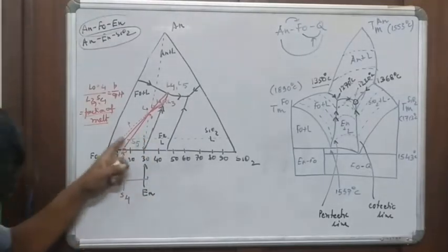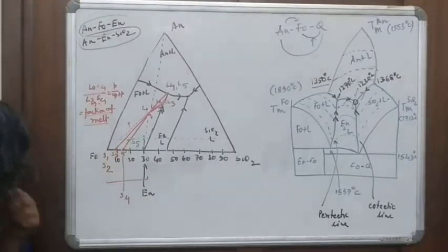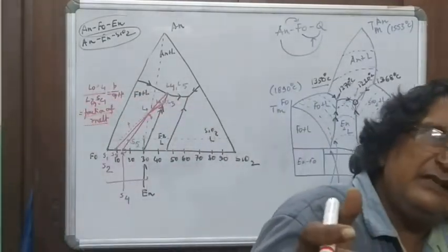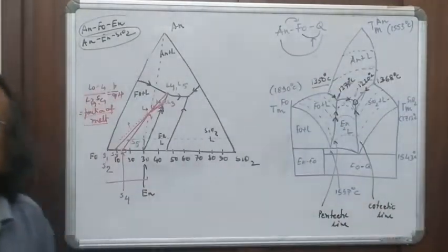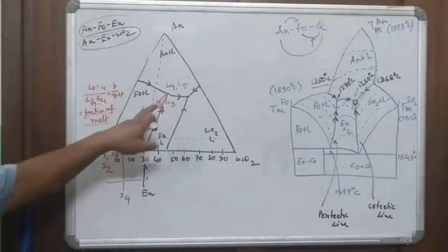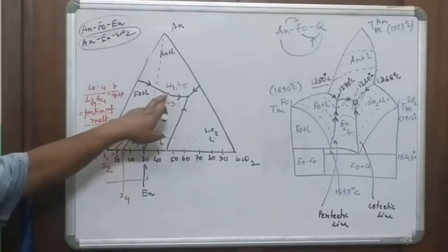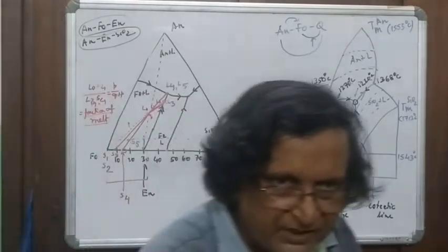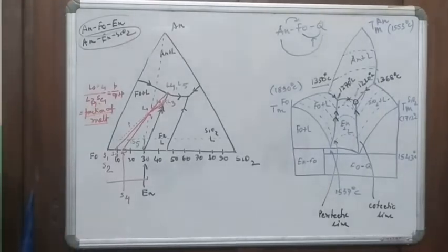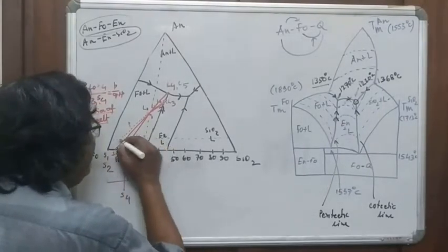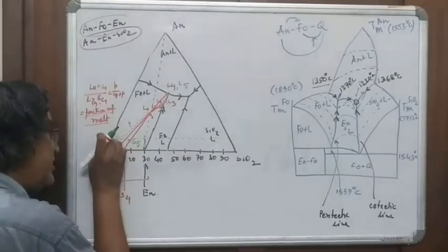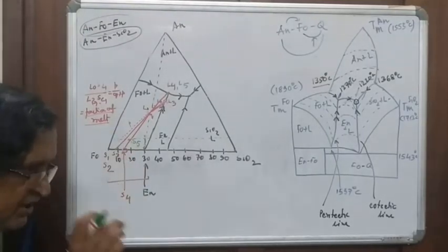So if it has moved towards the right, then the proportion of enstatite has increased. Forsterite has decreased. It is expected because you're still in contact with the boundary reaction curve, and therefore forsterite is continuously being reacted out to enstatite. And this S5 therefore is a very good example where you have started to precipitate anorthite in your rock.